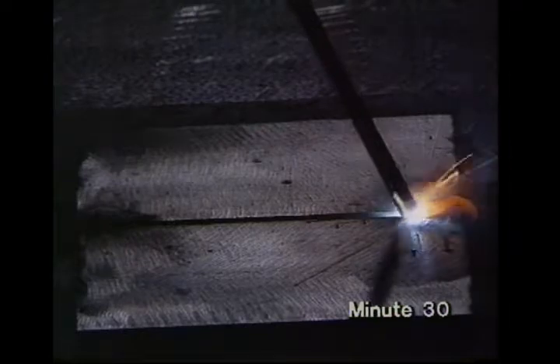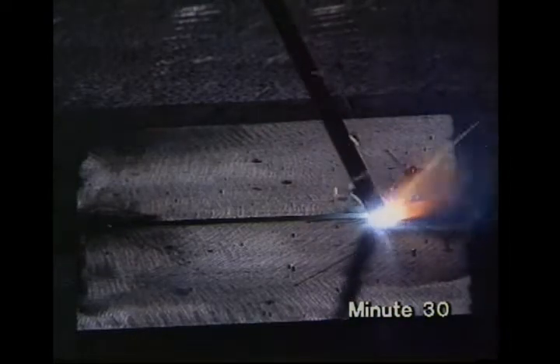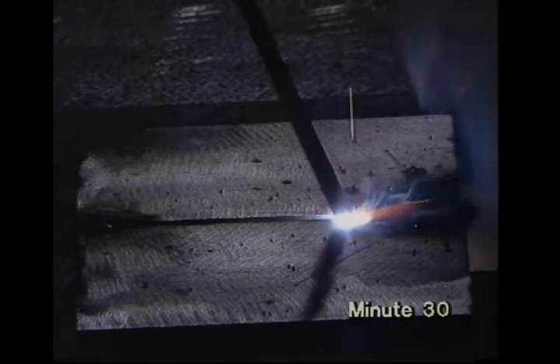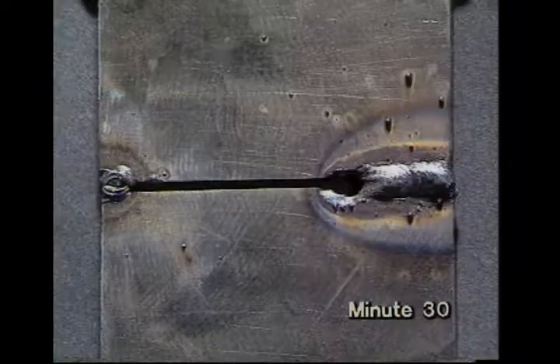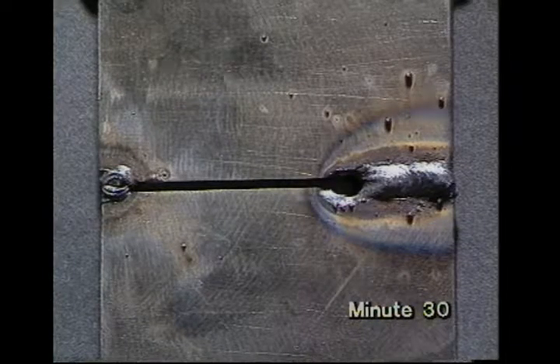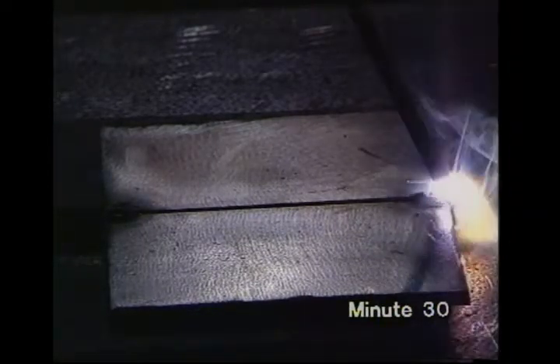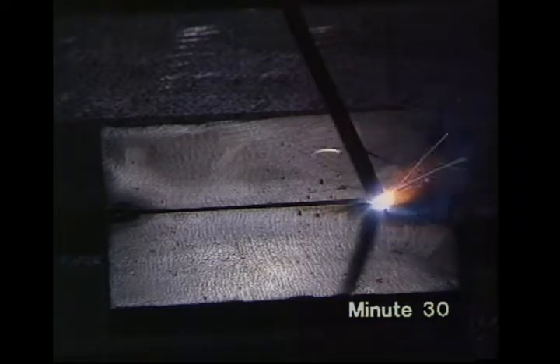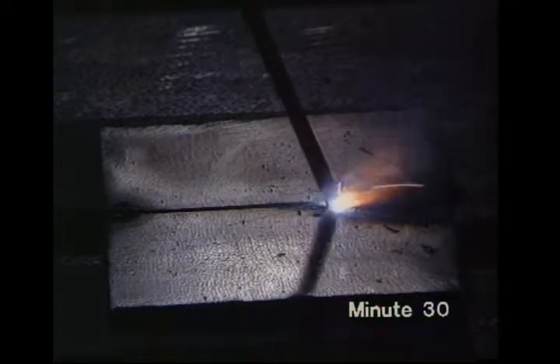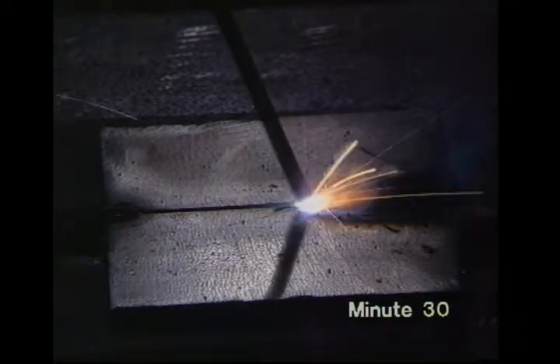But if the gap was too large, or the current too high, you would burn a hole. If Max finds that this is happening during welding, he flicks the electrode to put the arc out for a moment and let things cool down.